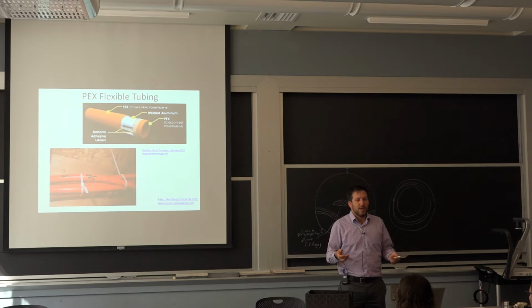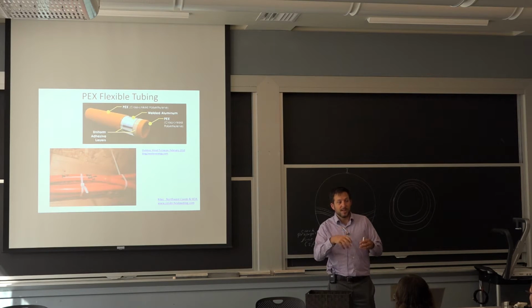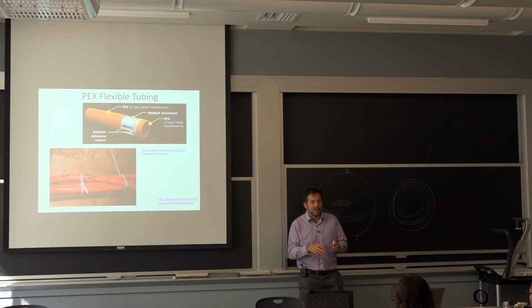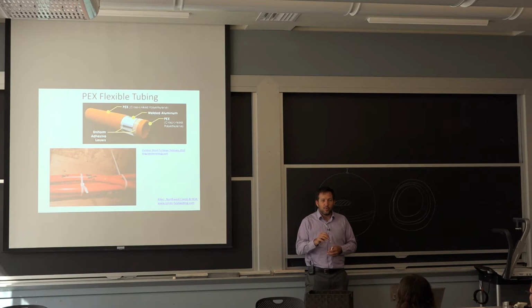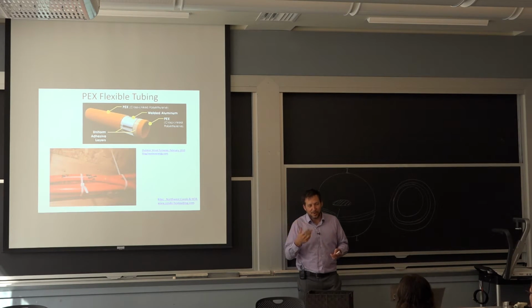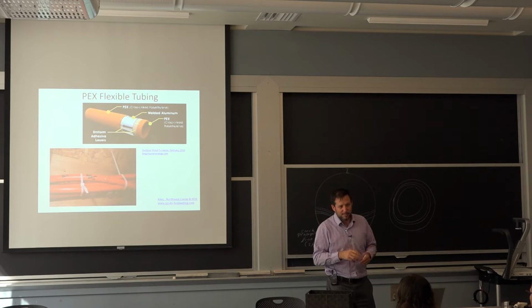Now it turns out that when you start having so much oxidation, the acidity inside the polymer goes way down. It's like you get to pH 3, and at that point, the aluminum corrodes very, very quickly. So it wasn't a barrier to the water. It just got poked into it.